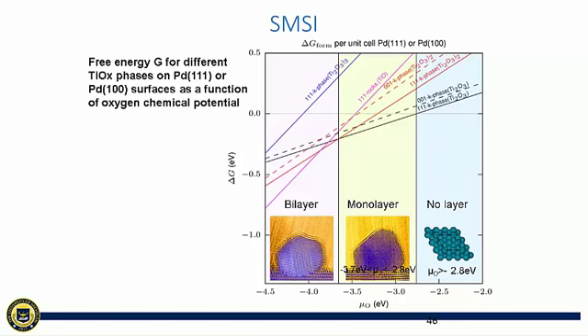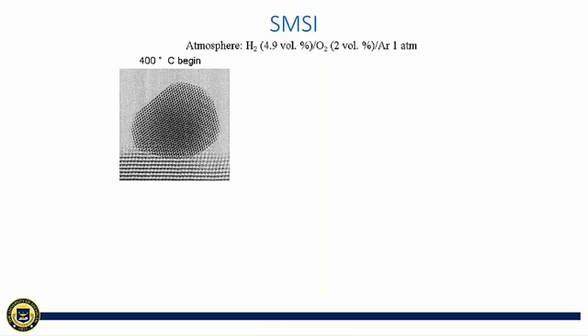If I mix 4.9% of hydrogen with 2% of oxygen in the gas cell, it corresponds to an oxygen chemical potential equal to minus 2.8 eV, and we did see the formation of the monolayer. If I mix 4.7% of hydrogen with 5.7% of oxygen, then it corresponds to an oxygen potential equal to minus 0.8 eV, and we didn't see any layer formation. So here the theory and experiment agree with each other very well.